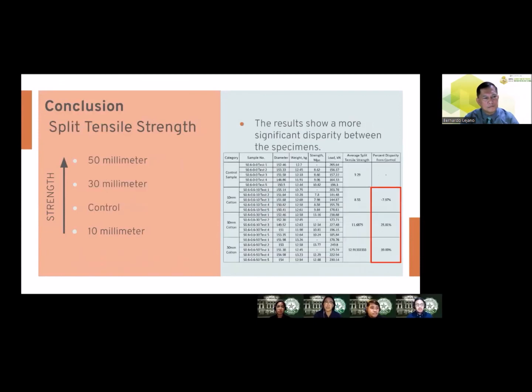The results of the split tensile tests show a more significant disparity between the specimens. The 50 mm samples had the highest strength, followed by the 30 mm samples. The average strength of each of the two specimens was higher than that of the control specimen. However, the 10 mm samples had the lowest average strength. Therefore, the trend seen is that longer fibers will contribute greater split tensile strength, and concrete with fibers that are too short will be weaker than traditional concrete.